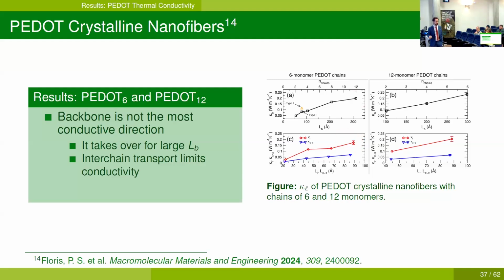And this was surprising, since we expected the backbone to always be more conductive, but it is not the case. So it appears the interchain transport from chain to chain is limiting the conductivity. On the other hand, something that we expected was that the pi-pi direction is the least conductive. The same things can be said for PEDOT chains of 12 monomers.